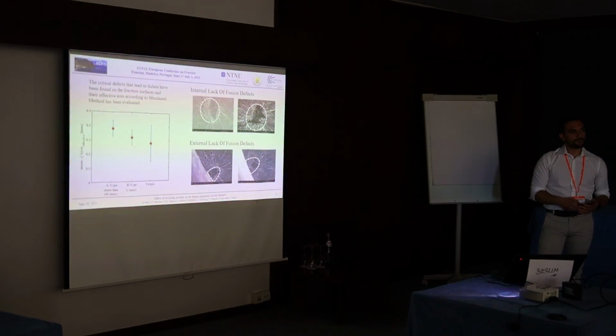So you have done this by the crack initiating defect analysis on the fractured specimen, right? Yes, we fractured the specimen and then measured the defects that were the most critical inside the component. Okay, thank you.